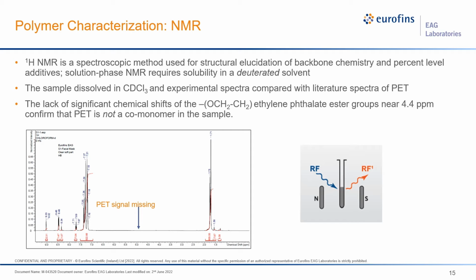We're also able to reference literature to look at a normal spectrum of PET. And when we compare that to our sample, we realize that there is a prominent chemical shift at about 4.4 ppm in PET that was not present in our sample. So again, this kind of further solidifies the minor differences that we saw between the sample and our reference spectra by FTIR spectroscopy.